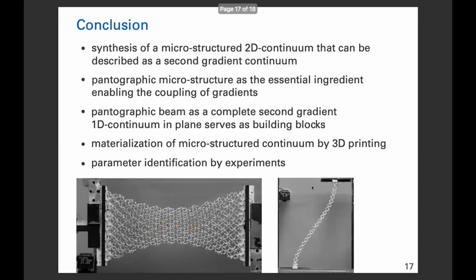Well, with that, I come to the conclusion of my talk. We synthesized with a pantographic beam a 2D microstructure that on a continuum level revealed to be a second gradient material. And we have seen that the Isola group has a fixation on pantographs not just because pantographs are so nice, but because pantographs are the essential ingredients to couple gradients in the material. And yes, we were able to materialize this microstructure continuum with 3D printing.